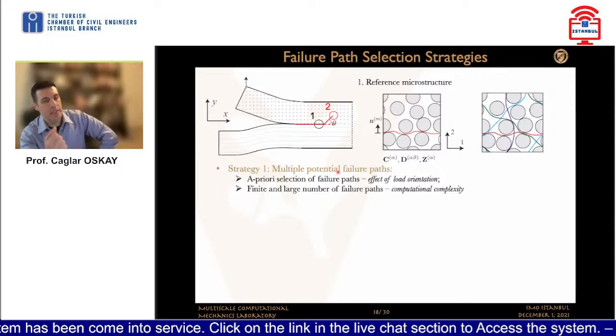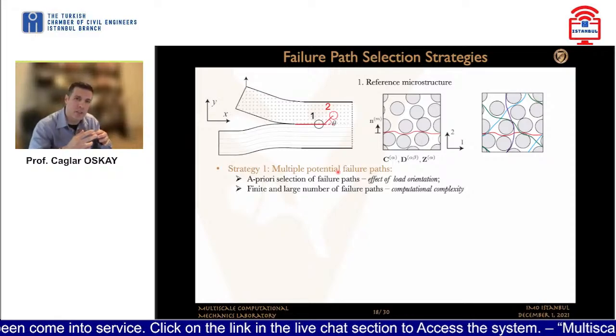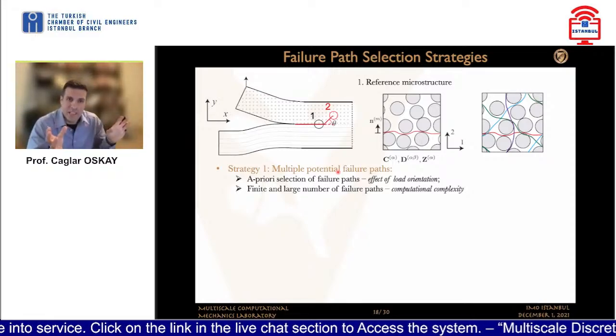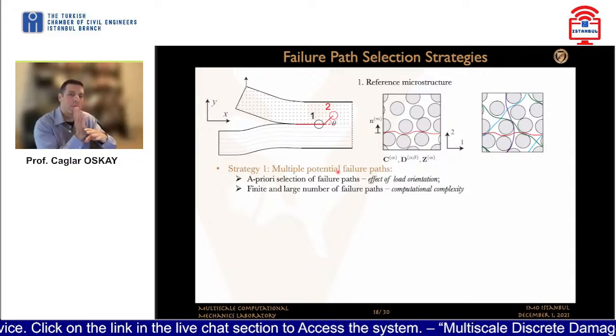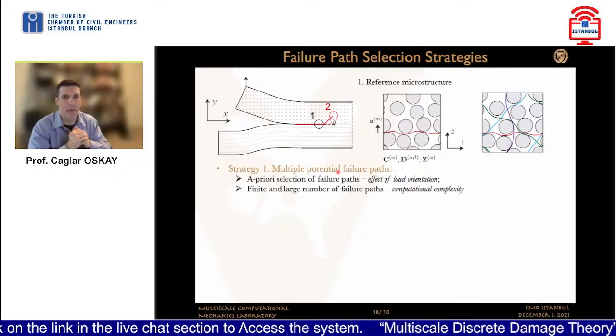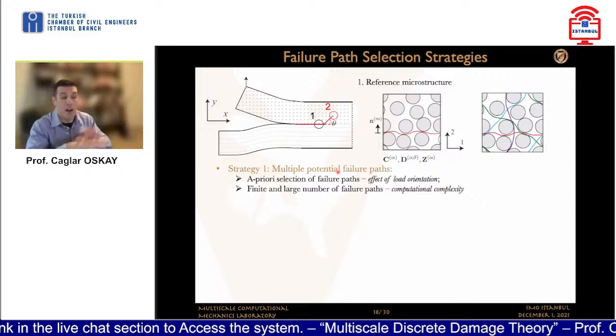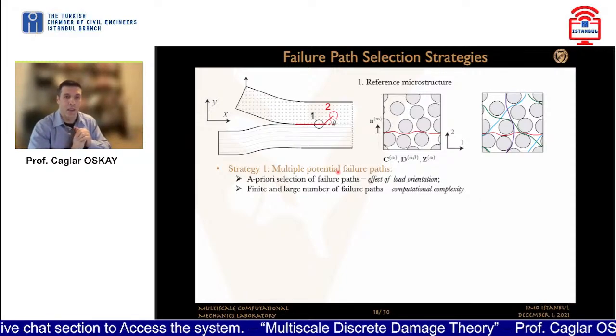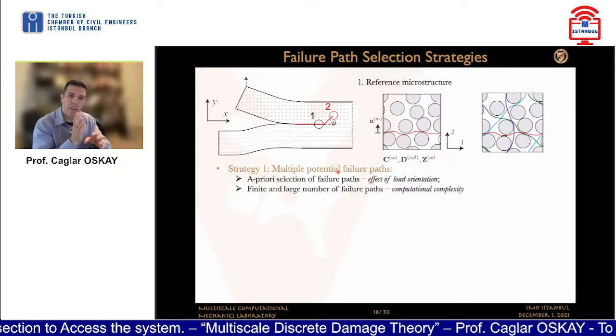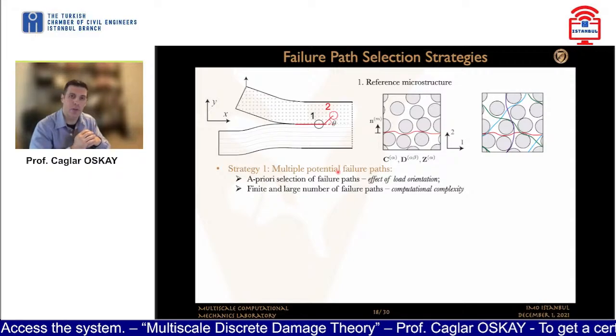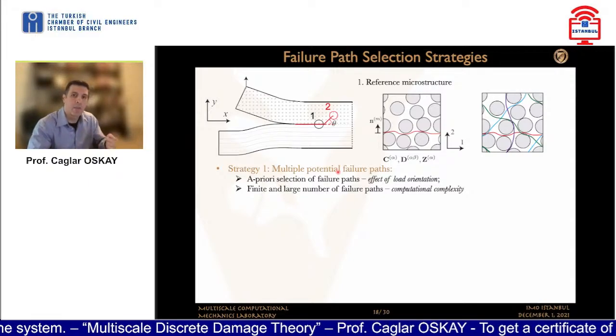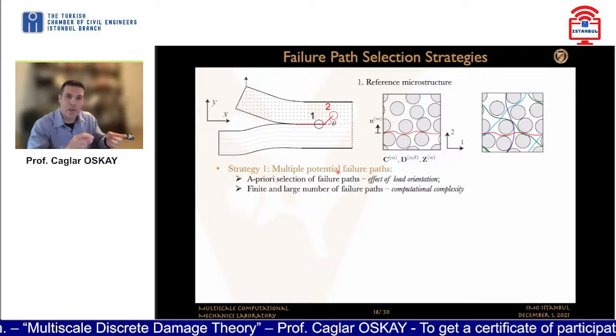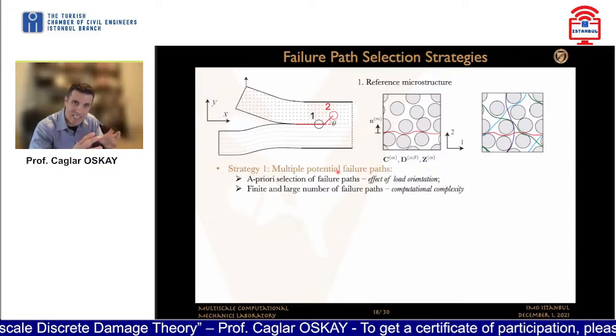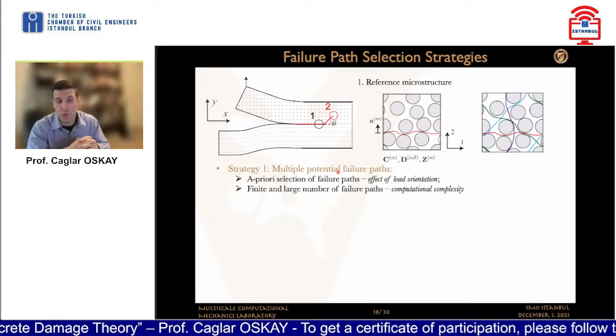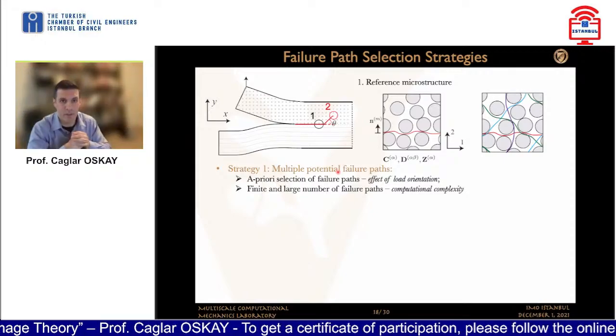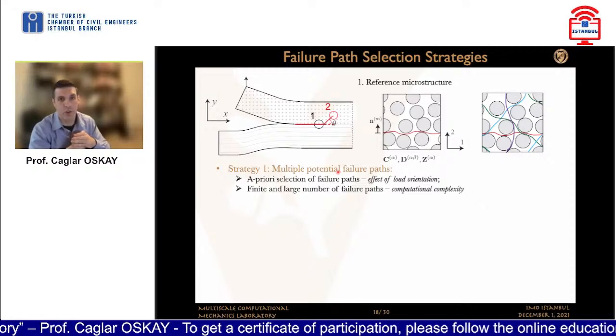So how can you deal with this problem? One strategy is to apply the classical MDDT that I've talked about before, but considering many, many different failure paths and incorporating them in the system. You select a large number of a priori failure paths. The issue is that as you select more and more failure paths to better capture the crack reorientations, the cost of the simulation also increases, because in that 3M system of equations, the M increases. And this is a dense system of equations, so the evaluation is order M cubed, which means it scales not very favorably with the increase of those failure paths.